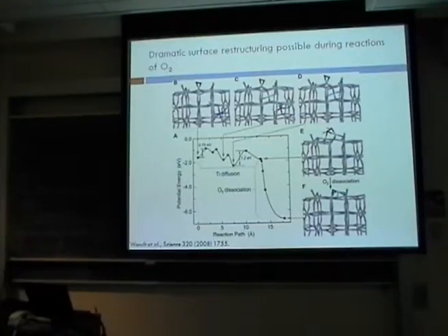So there have been a number of studies of reactions that are conducted not in the light that involve oxygen and water and hydrogen, in order to try to understand some of the elementary steps that are taking place during these reactions, at least the way they take place in the absence of light. One interesting thing that people have observed in titania and some of these other oxide materials is that it's a mistake to think about them as being a fixed matrix of a material. The titanium and oxygen atoms are very mobile and can move around inside the material to participate in reactions.